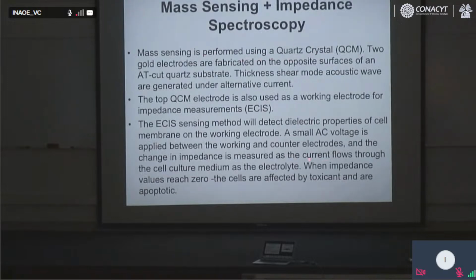The second technique is the quartz crystal. It's a resonator. Both are sensors. This is a very common resonator, where you use a quartz substrate and two gold electrodes are fabricated on the opposite surfaces of an AT-cut quartz substrate, and you produce an acoustic wave inside, named a thickness shear mode acoustic wave, and you measure the resonant frequency. When the cells are attached to the quartz crystal, the resonant frequency has a value. When the cells are dead, they detach, the sensor is much lighter, and the resonant frequency increases. So this is the idea of both sensors.